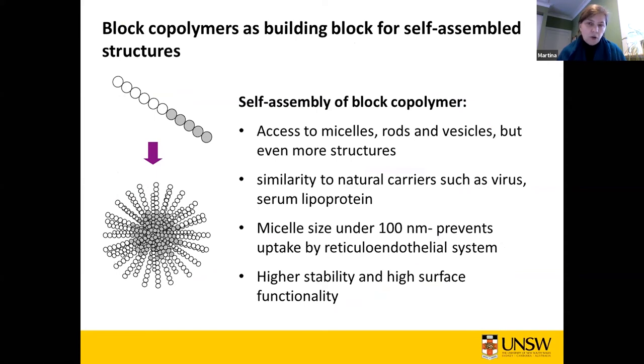So I want to show you how complicated that is using the type of particles I typically work with. And these are micelles. So micelles are made from block copolymers. So block copolymers are basically polymers that have two different parts. They have a hydrophilic part, so a polymer that is water soluble, and a polymer that is not water soluble. And when we put them into water, they start self-assembling by themselves. So depending now on that polymer, you can get different structures. You can get round micelles, you can get rods, vesicles.